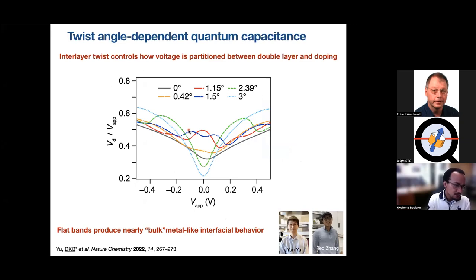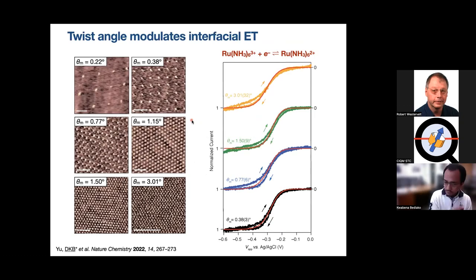And what this twisting is doing is making the bilayer graphene look electrochemically, look chemically, almost like a bulk metal, because it's generating this large density of states close to the Fermi level. And I'll show you how important it is to match where those flat bands are to the chemistry that you're trying to do. I'll show you that in a little bit. But the first thing we learn is that this twisting is making the bilayer graphene behave almost like a bulk metal, electrochemically at least, okay, and it's controlling how voltage is being partitioned between the double layer and the quantum capacitance.